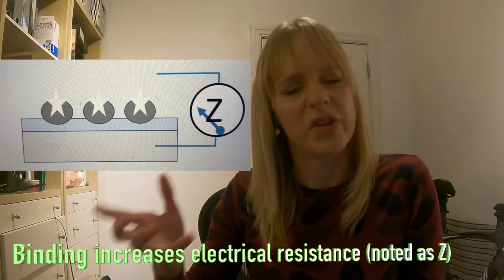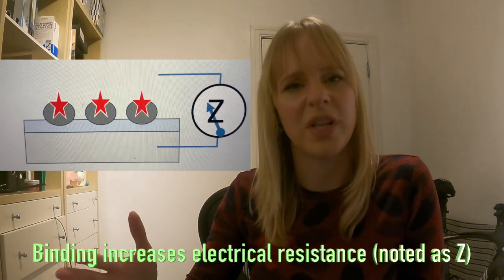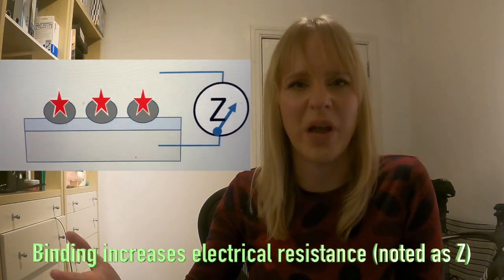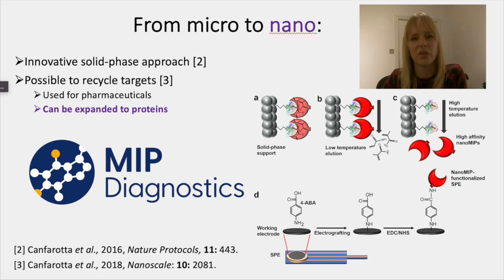So even though molecular imprinting has been around for quite a while, it wasn't until the 90s that this really taken off, because then they started looking at non-covalent imprinting. And at the beginning of my career, I actually used a process where we produce microparticles, which generally lack in affinity, are not quite as good as the nanoparticles that we work with at the moment. But what you can briefly see here in this animation, what you would get is that you would have a microparticle with these binding sites, and as soon as you get binding to it, you would see a change in electrical resistance.